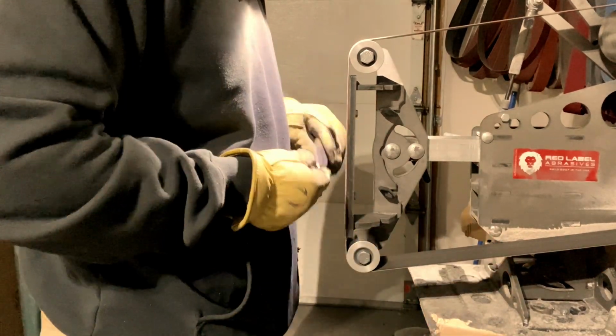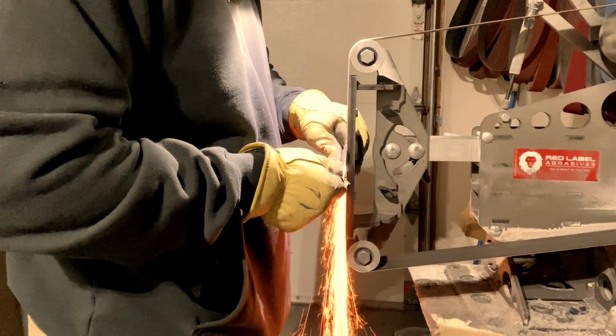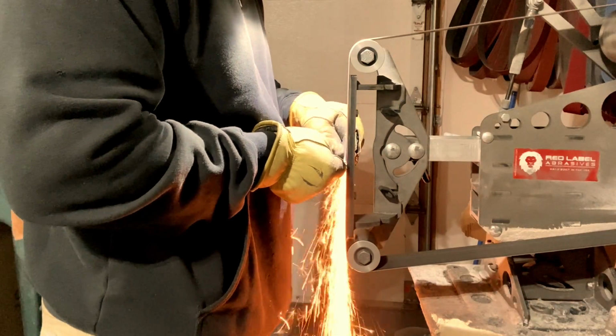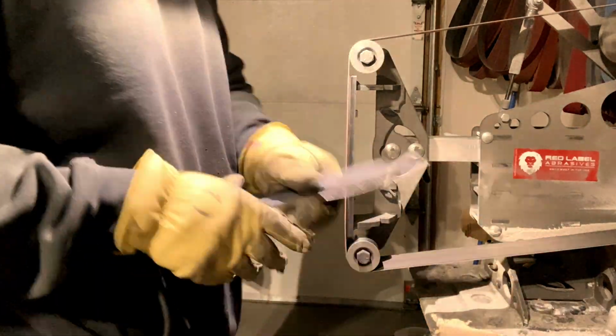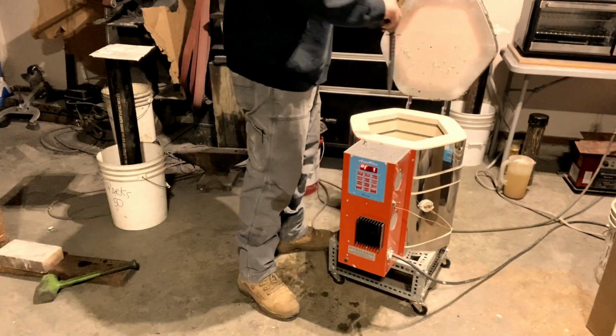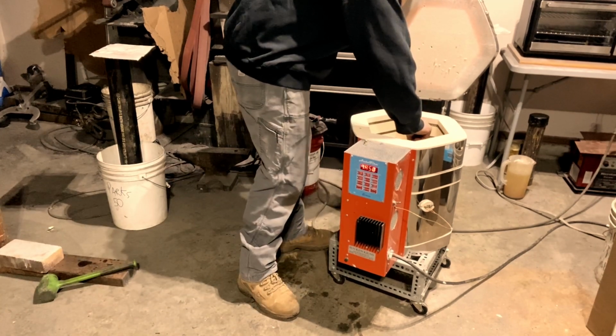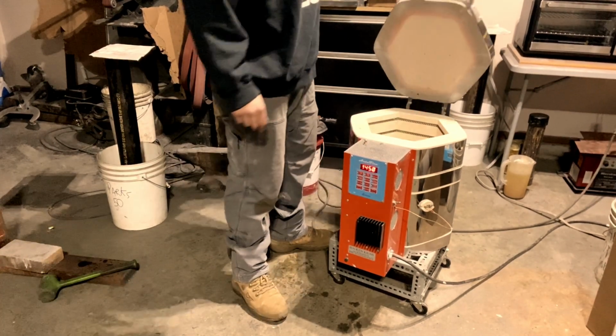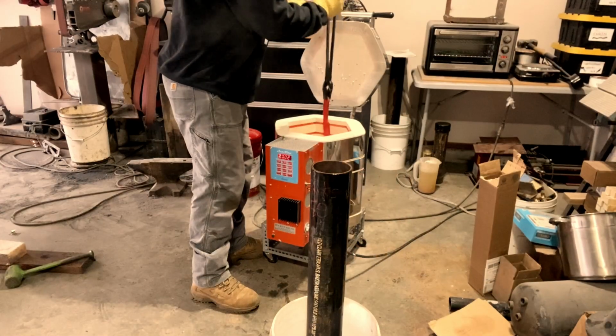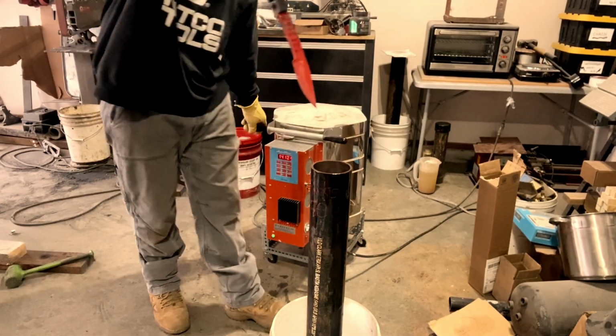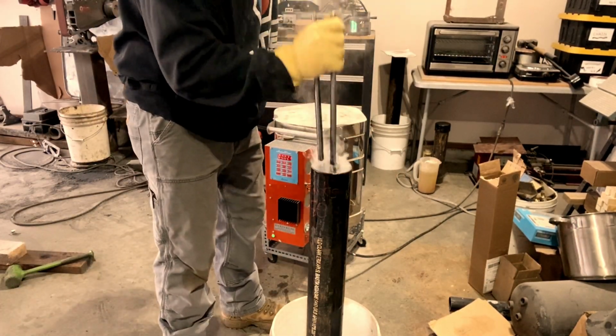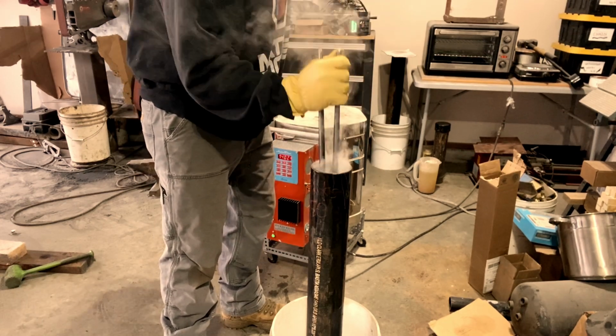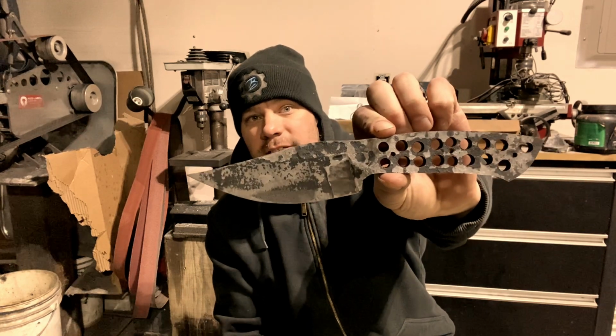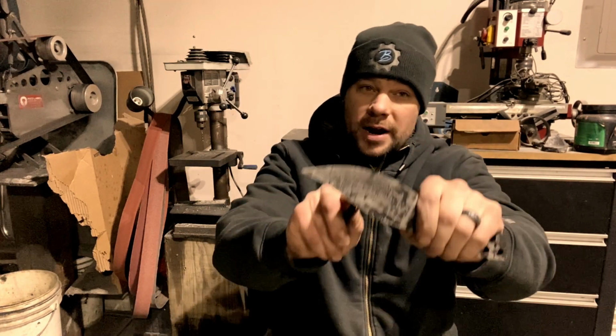for heat treat. I did 4 normalization cycles off camera, starting at 1540 and working my way down in temperature to 1425. And I quenched the blade at 1425, which is important because you want to austenize at the lowest temperature possible. If you quench too hot or soak the blade too long, you can put enough carbon in solution and basically erase the pattern. All right, well, the quench went great, as I expected. The blade hardened up nicely.